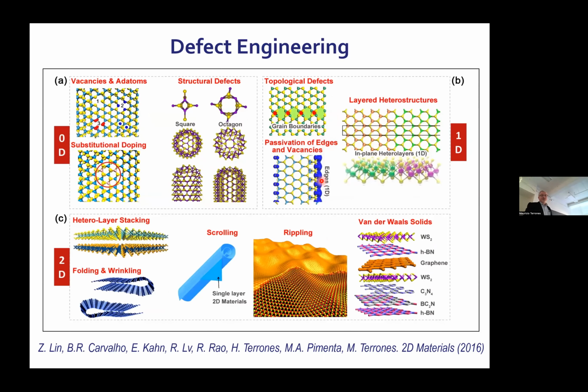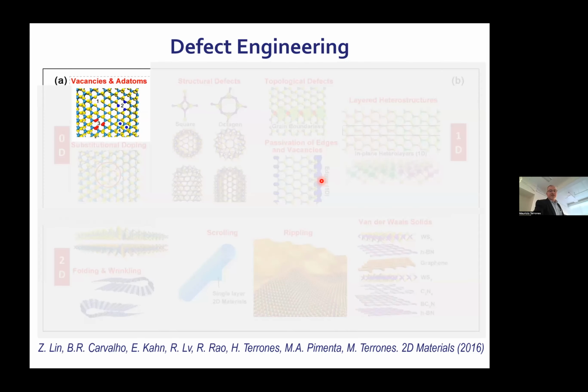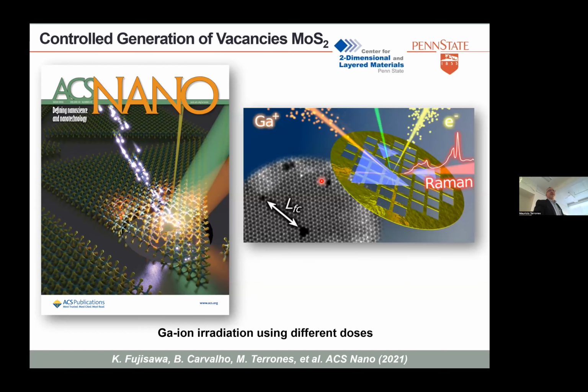Okay, let me just move on. The next thing is trying to understand the vacancies. Is there a way you can measure the number of vacancies that you have in the system if you do some spectroscopy, right? So we tried Raman spectroscopy for that. And then we did this work using gallium ions, but you can do it with any type of ions. So what we did is we deposited on a quantifoil grid.